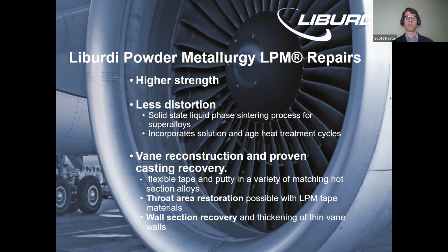We're going to talk a little bit about Liburdi powder metallurgy, or LPM repairs. The LPM is a higher strength alloy than typical weld alloys, and usually you're going to see less distortion. It's a solid state liquid phase sintering process for superalloys, and what that means is you don't have a local heat like you would in a welding process. And there's certainly areas on all components where welding is appropriate, and we also often do hybrid repairs, but there's also large areas for wall thickness recreation where you just would never want to do welding because you'd have way too much distortion, especially on the aeroderivative components that we're going to talk about today.